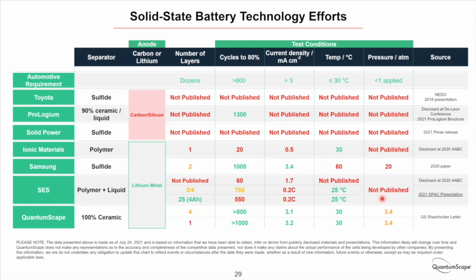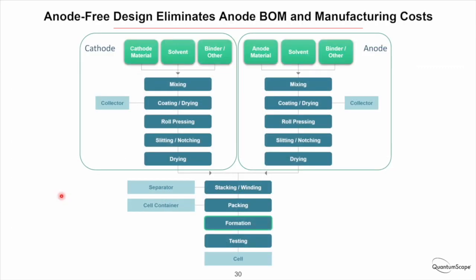So without going into all the details and boring you, what I'll just point out is that these technologies have either had to sacrifice in terms of cycle life, in terms of running at high temperature and pressure of 20 atmospheres and 60 degrees C, or low current densities of like C by 5 rates, which wouldn't enable fast charge. So this is the landscape of some of the most serious players out there. If I've missed anything or gotten anything wrong, I haven't heard it since we put out this chart several months ago. So certainly open to it in the Q&A if you know these players have published anything more recently. So I think we've got a pretty compelling technology.